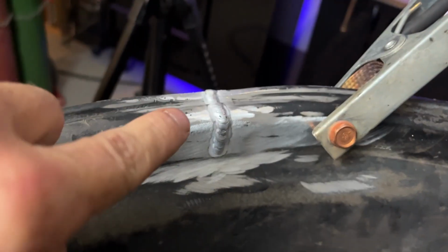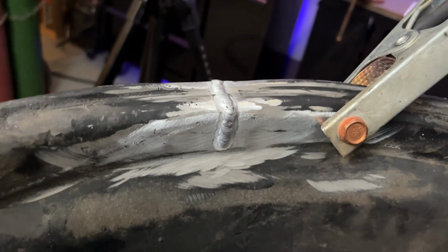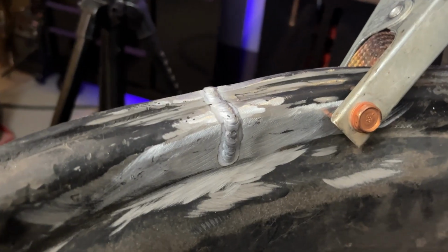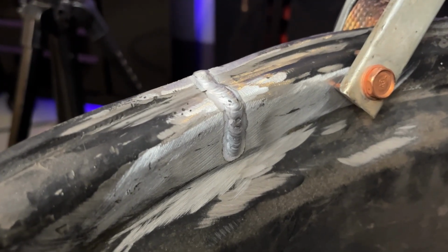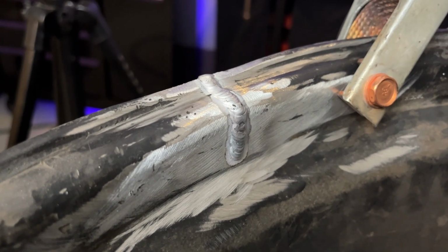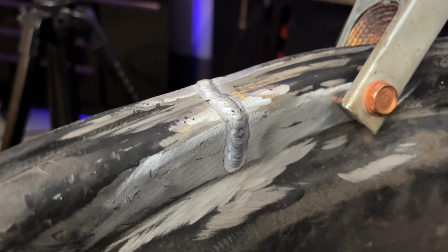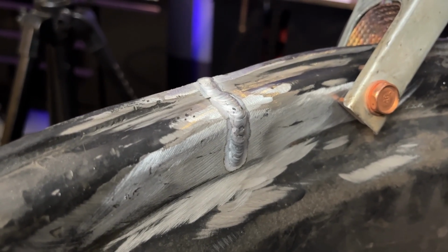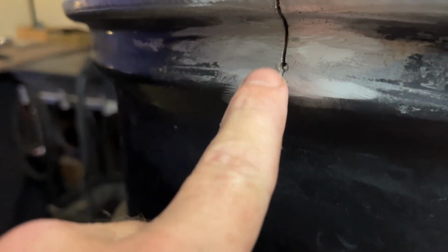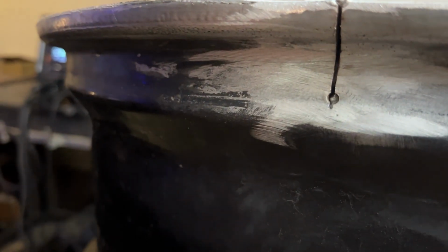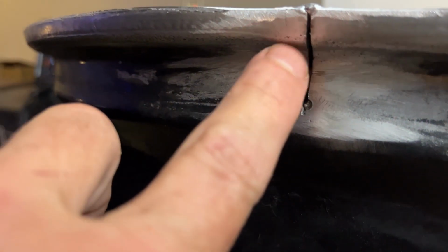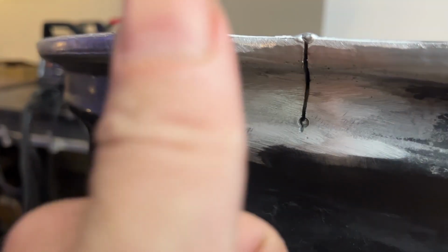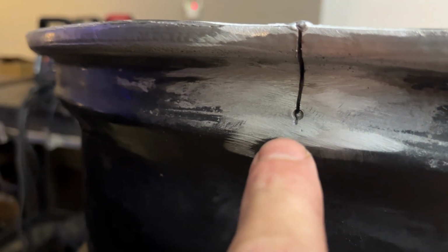Well, it definitely pulled some trash. You can see the speckles, the black pepper in the puddle. That definitely was trash pulling out of that joint. So we made the best of it. I let it eat in there, and we got a decent looking bead on that side. However, we are not done, because as you can see here, we did not penetrate all the way through the joint, which is fine. We're just going to have to go in here and back grind this until we see bright metal on the other side, and then we can get our weld to go in it. We'll overlap and not have any more leaks coming from this spot.